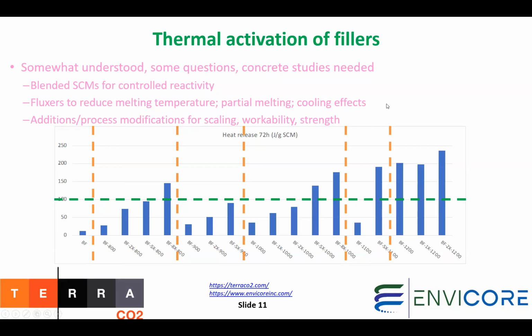So we have now reduced the melting temperature by 400 degrees, and I put melting in quotes because melting in glasses is a little complicated, especially in these heterogeneous systems. The interesting thing here is, again, those of you who know ceramics will figure that this is actually very obvious. The challenge is not in reducing the temperature. The challenge is in actually understanding what is happening, what are the mechanisms of the melt itself.